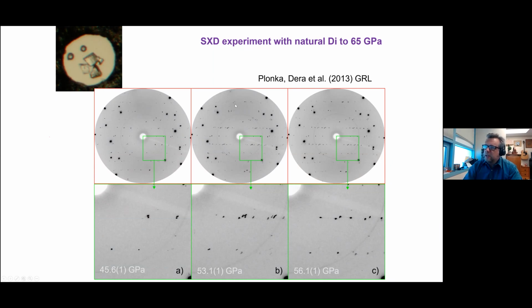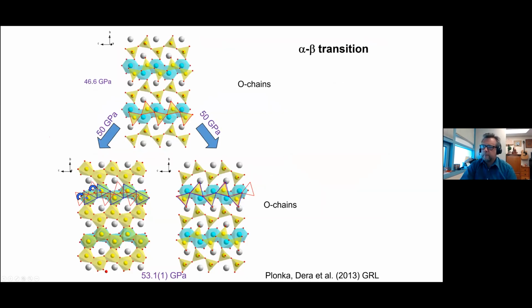There's an intermediate state where we have peaks of both the low and high pressure phase present. So there's more peaks in the middle here. And then at about 55 gigapascals, the low pressure phase completely transforms and we only have peaks of the high pressure phase. If you look at what atoms are doing, it's topologically quite similar to what orthopyroxene did.